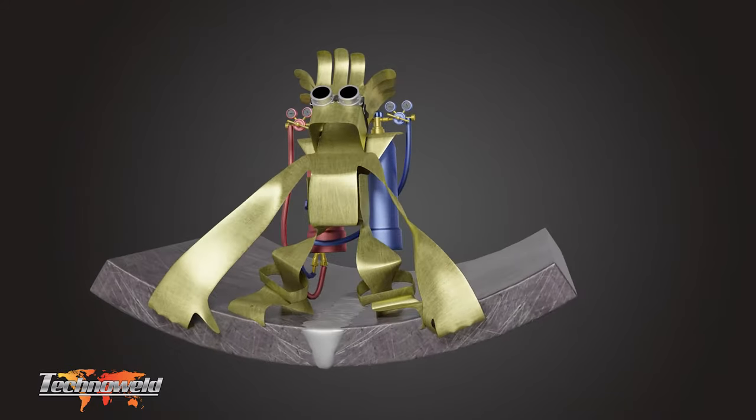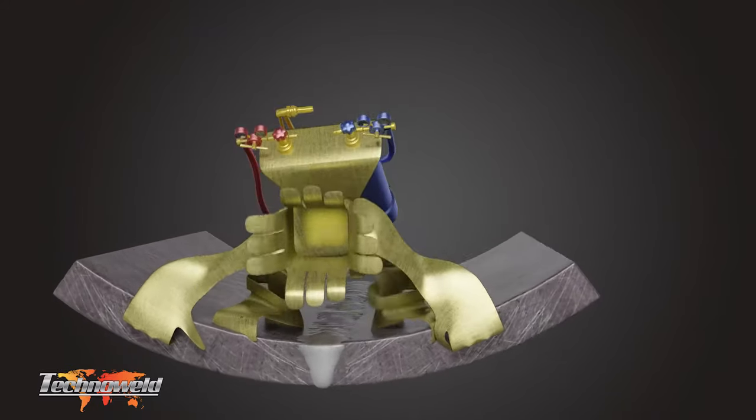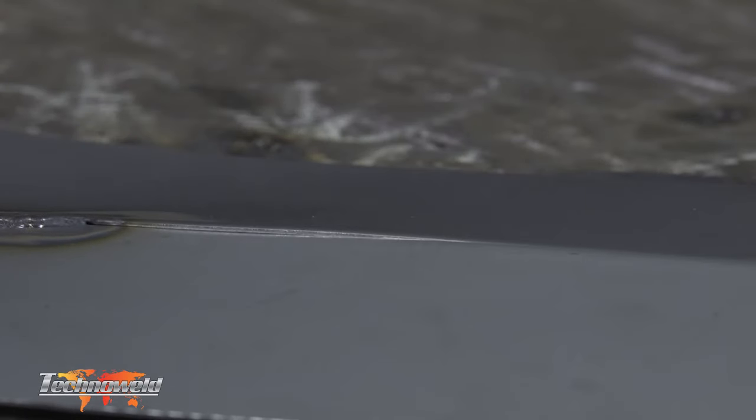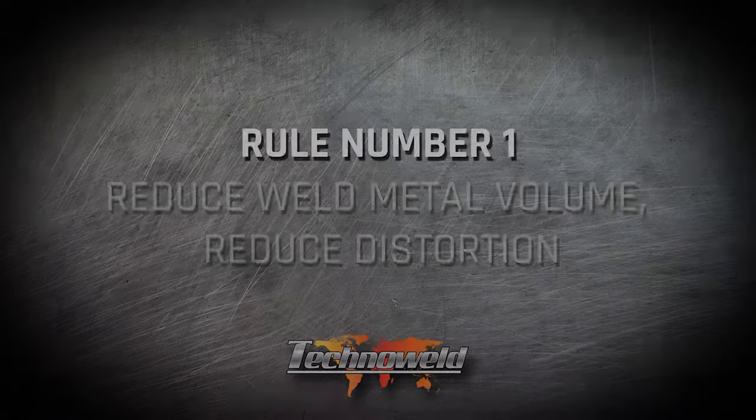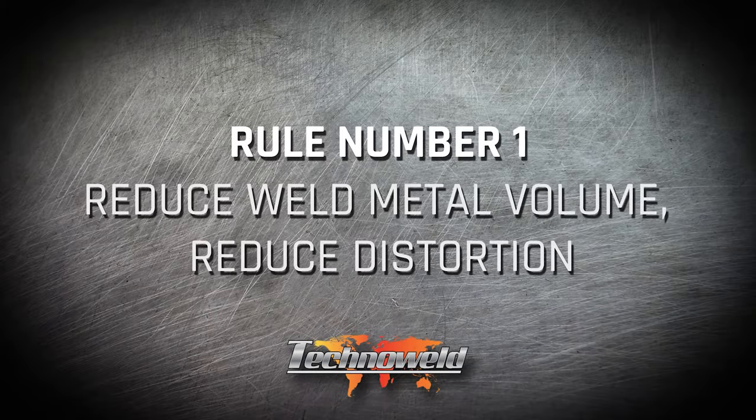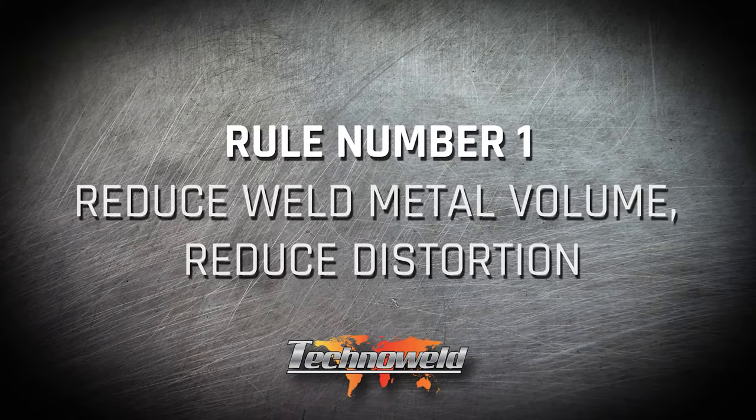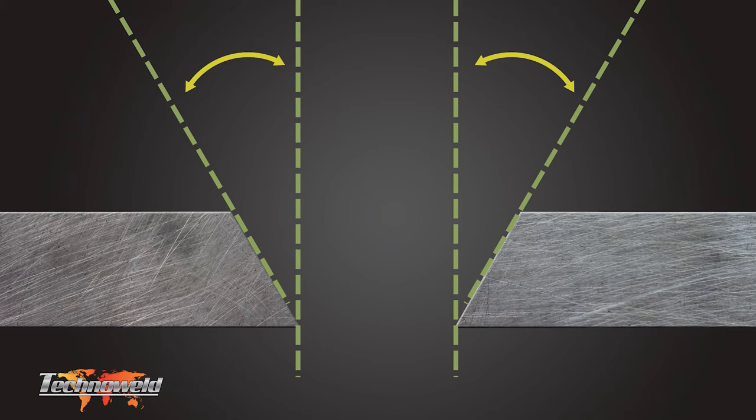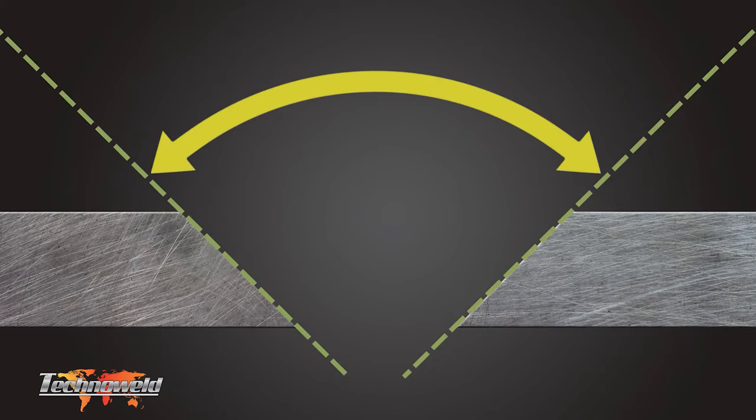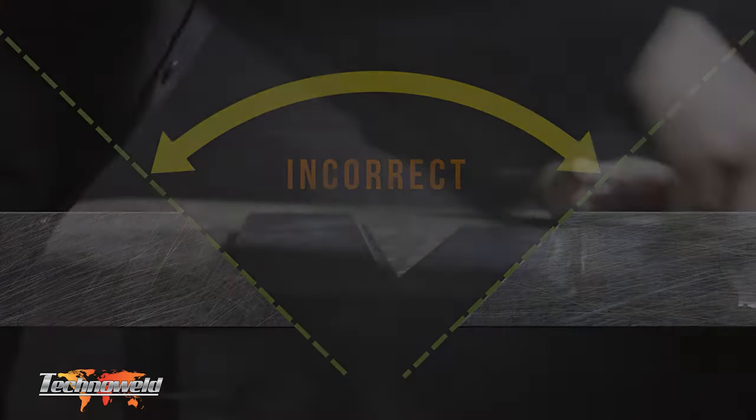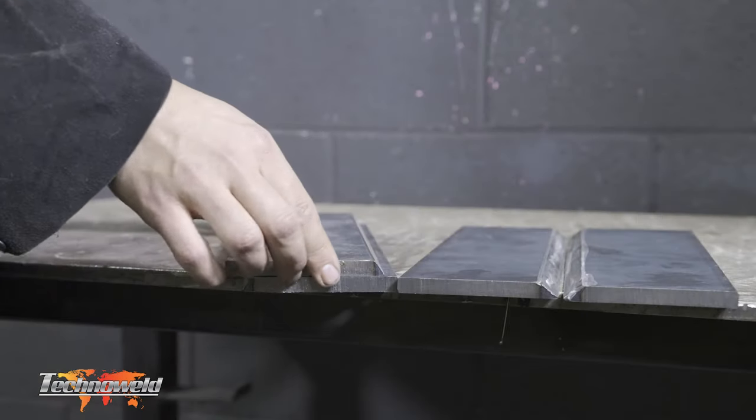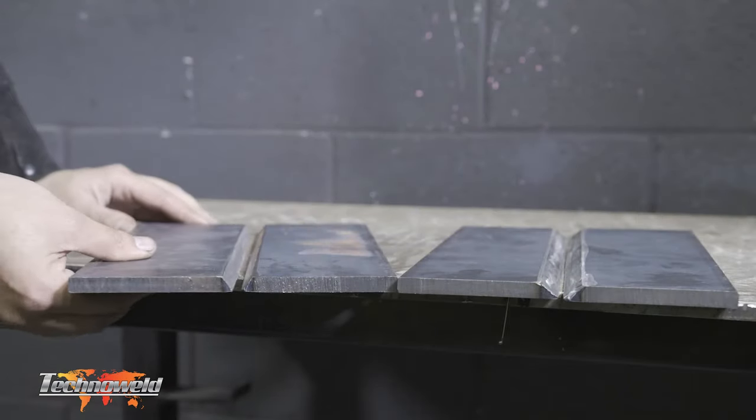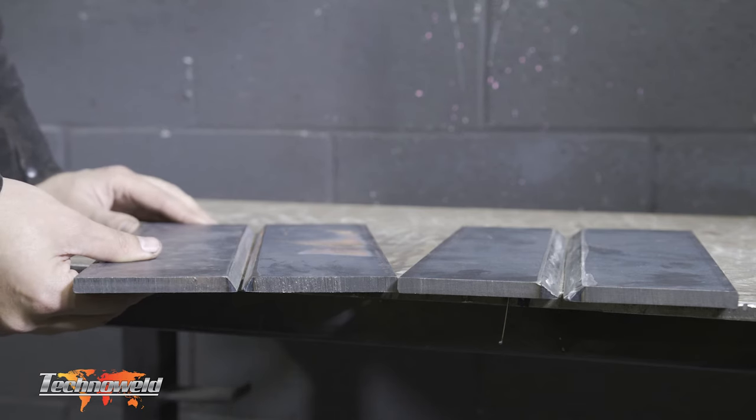If this weld is performed without some control, the two plates will distort. No consideration was given to distortion, so it appears to ruin all your hard work. Uncontrolled heat distorts the weldment. Rule number one: reduce weld metal volume, reduce distortion. Weld metal volume is both the size of the weld and the length. Depending on the type of joint and material to be welded, prepared edges will angle between 30 and 45 degrees. Excessive angle on the weld preparation can result in additional weld metal volume and induce more contraction, leading to more distortion. Out of these two examples of single v-butt joints, the example on the left has the ideal bevel angle of 30 degrees for low carbon steel.